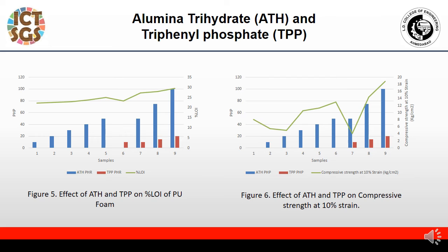The fifth flame retardant is alumina trihydrate and triphenyl phosphate combination. Here figure 5 and figure 6 show the effect of ATH and TPP on polyurethane foam. In figure 5, it shows the percentage LOI, which increases when both ATH and TPP are used in combination. The increase of the percentage LOI in combination is comparatively higher than when only ATH is used. Figure 6 shows the compressive strength at 10% strain, which also increases when both are used in combination.